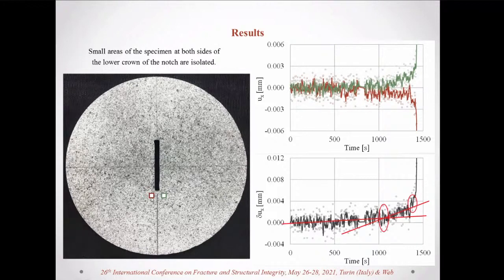Two small areas on both sides of the lower crown were isolated, and their displacements along the horizontal axis were plotted versus the time of the experiment, and also their difference. And we obtained this graph, which can be clearly divided into 3 stages. The first slope change observed is at about 1,000 seconds, in other words, about 70% of the maximum load for the specific specimen, and we assume it corresponds to the initial formation of the crack front, while the second slope change corresponds to its propagation.